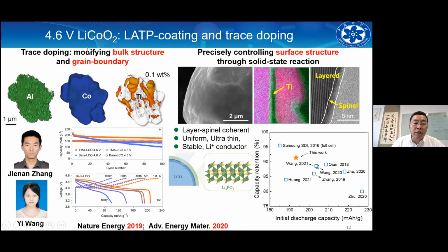And also the high voltage lithium cobalt oxide is very important for consumer electronic device applications. Last year, we published a solid electrolyte coated LCO, which can deliver high capacity and reasonable cycle life. Protecting the surface is very important to decrease the surface oxidation ability. This is a very practical way and is already scaled up now.